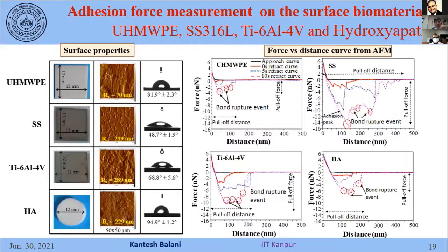So we have taken all these materials, which are polymer, metal, and ceramic. Here we also observe their roughnesses, which are of the order of 100 to 200, 300 nanometers, more or less similar, because the bacteria itself is around a few micrometers. They also have the typical surface wettability characteristic. But what is interesting is on the right hand side. Once I have this particular cantilever, I attach a bacteria on the bottom and bring it in contact with the substrate. I keep it for 0 seconds, 5 seconds, and 10 seconds, and then we detach it. And once we're detaching it, we are seeing this response.